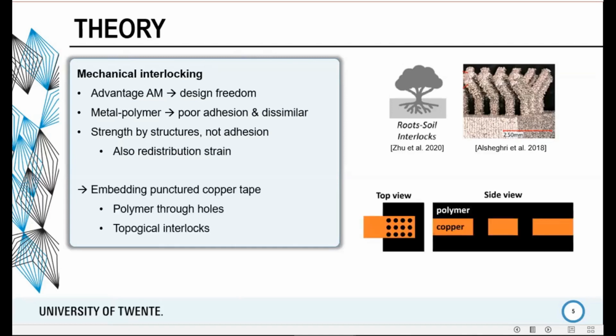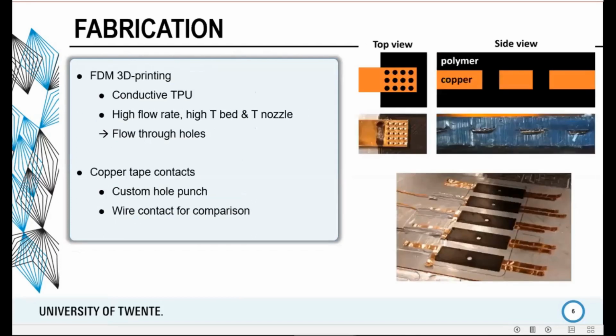In this work, we propose to do this with punctured copper tape. So we take normal copper tape, we make holes in it, we put it in the sample during printing, and when we print on top of it, the material flows through the holes and really creates this interlocking, this connection through the materials by itself. We print with standard fused deposition modeling printing, and we use standard copper tape. And during printing, we use high temperatures and a high flow rate to really make sure that the material flows through the holes. So in this cut through, we've made a sample, we've made a cut through, you can really see that the material is going through the holes in the copper tape. So it's really connecting on both sides, creating this link, which has to be broken to break the contact.